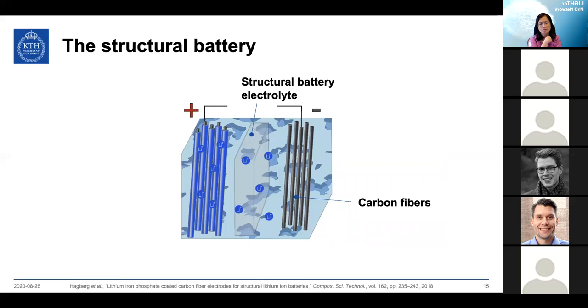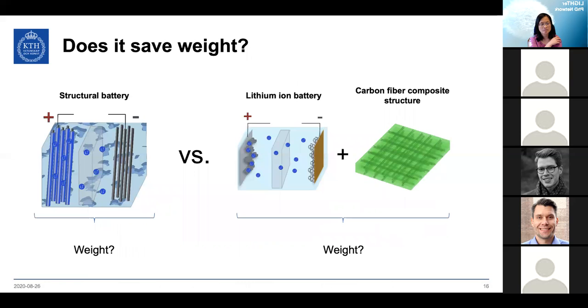So we can swap out the copper and graphite powder of the negative electrode and replace it with carbon fibers. And we can alter the electrolyte to create a true composite material with those fibers and the structural battery electrolyte. But this is only 2 of the 3 parts we need for a functioning battery. We still need a positive electrode, which we would create by combining carbon fibers and lithium-rich powder. This would complete our battery and further strengthen our structure due to the extra fibers. The question is then, will this structural battery save weight versus a lithium-ion battery and carbon fiber structure?